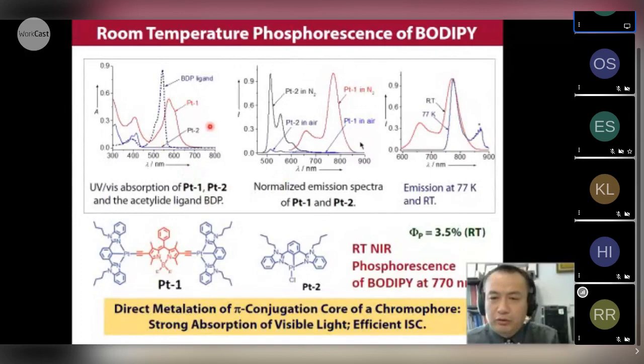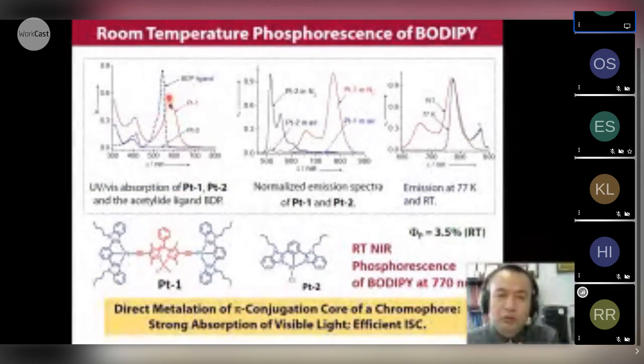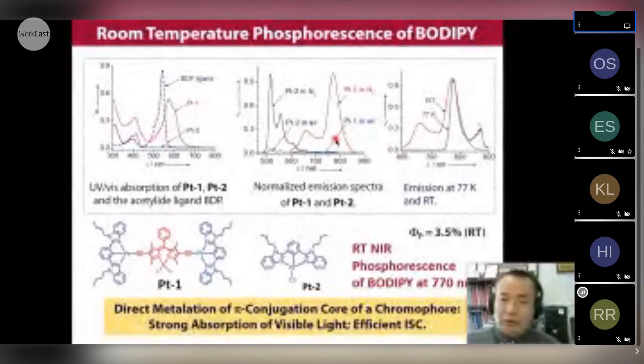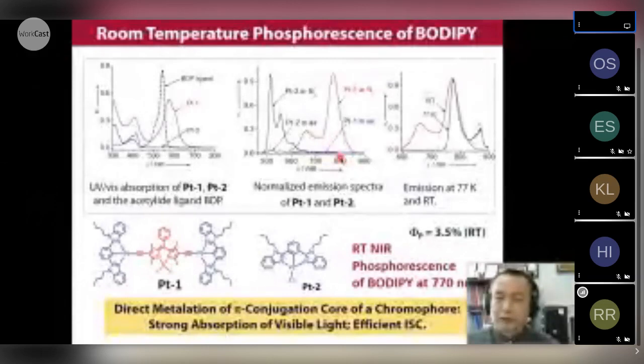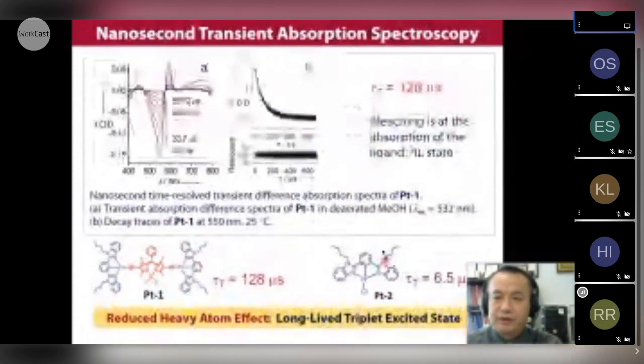So with some routine spectral study, we can see the absorption of this complex is very strong in the red yellow region, much stronger compared to the model complex. The model complex, the PT2, only gives very weak absorption in the UV region. The new one gave a very strong near IR emission close to 800 nanometer. That means we have very efficient intersystem crossing. Otherwise, we won't observe any strong emission in the near IR region. The non-radiative decay will deactivate the T1 state. We will not observe strong phosphorescence emission. That means the direct connection method is good to have efficient intersystem crossing.